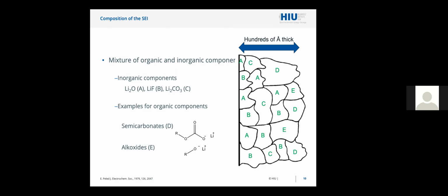So this picture, which gives us a pretty good idea of what is in the SEI, was actually made by Emmanuel Peled in 1979. Most likely made the year before, because at that time it took more than a year to publish a manuscript. It was not that fast like it is now, but we are still more or less there. So the SEI is a layer which is a few hundred angstrom thick, so a few tens of nanometers, and it's a mixture of organic and inorganic components.